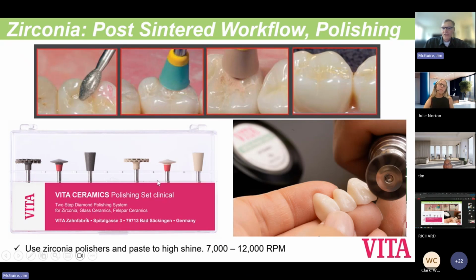But there are many polishers available on the market specific for zirconia, and diamond burrs, rotary instruments specific for zirconia. Make sure that you use those dedicated for zirconia. If you're adjusting them, make sure again you're going to use low speed. It is possible that you can shock monolithic zirconia, if you're adjusting intraorally or outside the patient's mouth, if you're using too much pressure, too high RPM. Just like a glass ceramic restorative material, you can shock it, even though zirconia is better at absorbing that shock. You can still cause it to microfracture, and you build up a lot of energy.